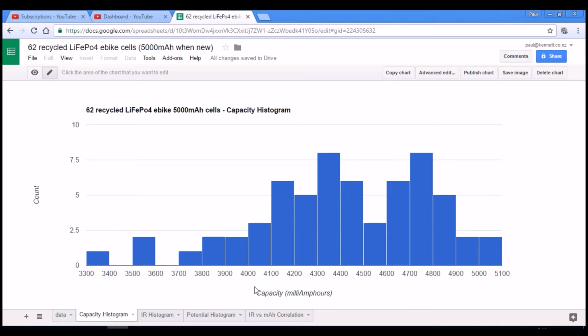So it's all those numbers sliced up into buckets of 100 milliamp hours. So you can see I've got quite a few that are around the 4,300 milliamp hours, and I've got another hump here around the 4,700 milliamp hours. So the interesting thing there is that these cells have come from three different e-bikes, and what I am guessing is that this hump here represents one of the e-bike packs that was not as old and thrashed as these